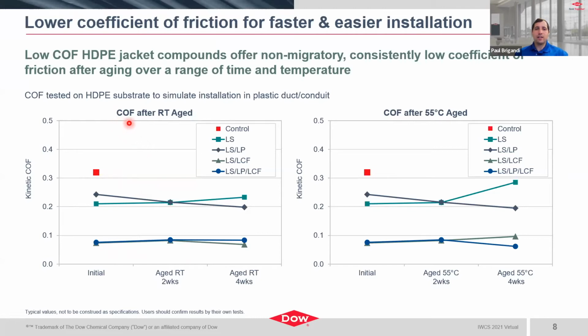We've aged these cables for up to 4 weeks at room temperature, so relatively close to 23 to 25 degrees C, as well as some elevated temperatures close to 55 degrees C. And so we have our control, which we measured initially. And you can see its kinetic coefficient of friction is just above 0.3.